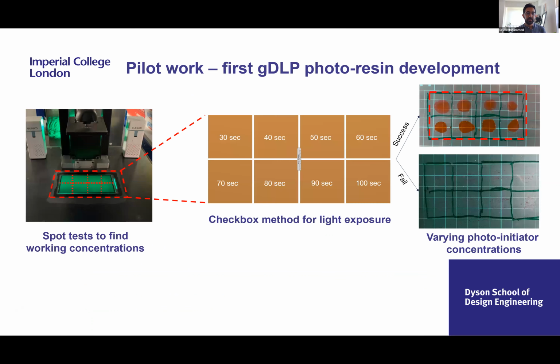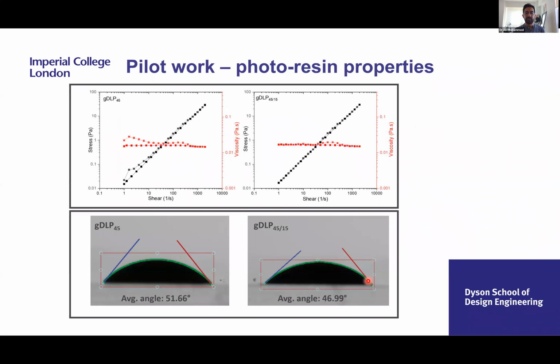So first, g-DLP photoresin development. The initial steps were to do spot tests, and these spot tests consist of an array of different light exposures on the same build. Here we try to see what is the minimum light exposure we need to get a certain gel from our resins. This is very important, as this gives us the starting point for the exposure that we're going to need per layer. Every time we get a failed attempt, we increase the photoinitiator or increase different concentrations within the resin. Here you can see that we had a successful batch, and here you can see that we didn't, and that was during photoinitiator optimization.